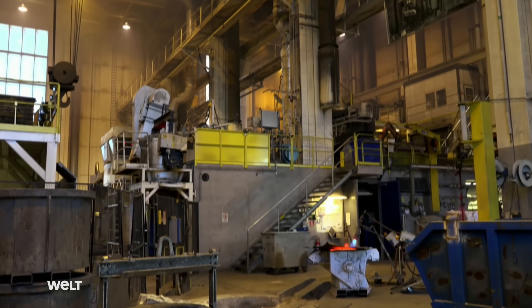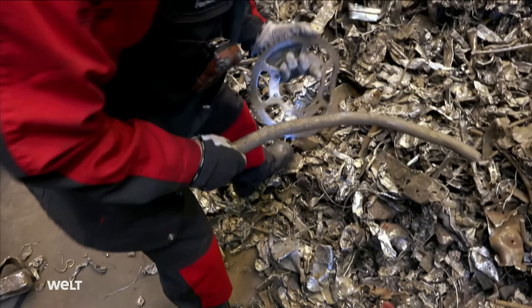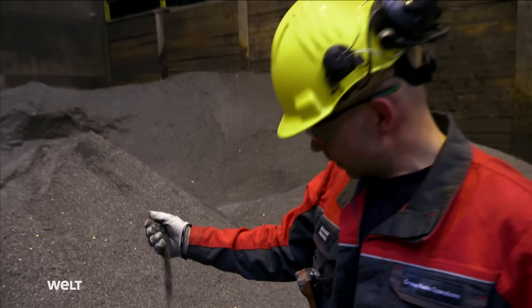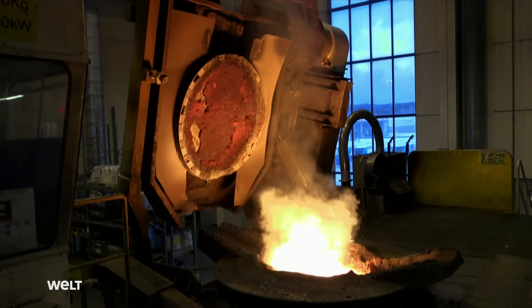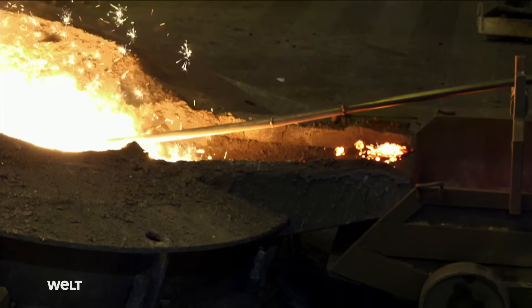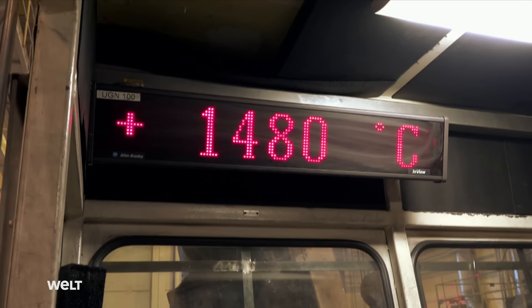This huge site hosts almost 3,000 employees working across 265,000 square meters. The center of everything is the foundry, where the world-famous Swedish steel is cast. Machining chips are cleaned and melted again — all scrap is recycled in-house. The steel is melted in crucibles; there are always two heated up, and the current one holds 20 tons of liquid steel. The slag — the dirt that settles on top — is removed repeatedly, and the temperature is constantly held just below 1,500 degrees Celsius.